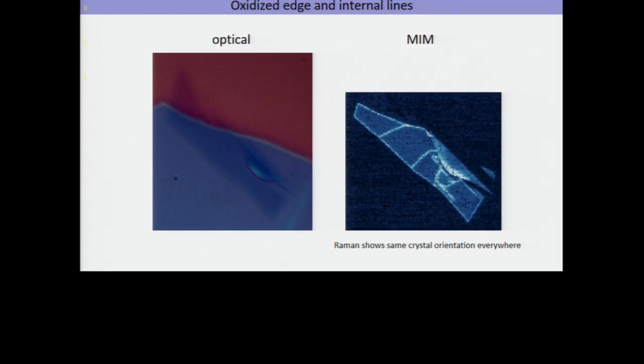But we can't see these cracks in any other way. We don't know that they're there optically or in AFM. We only see them because they produce these conducting lines inside the sample. They should have double the conductance, right? Or more, yes. Well, the cracks.